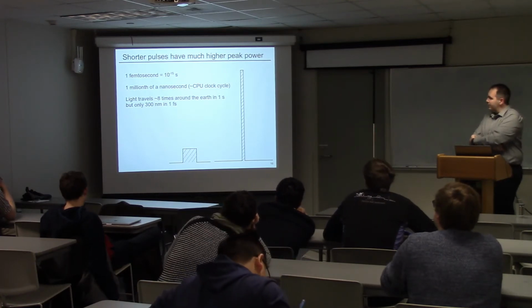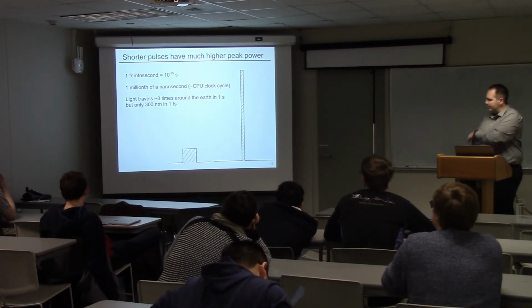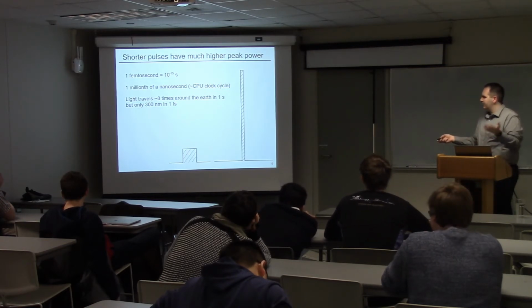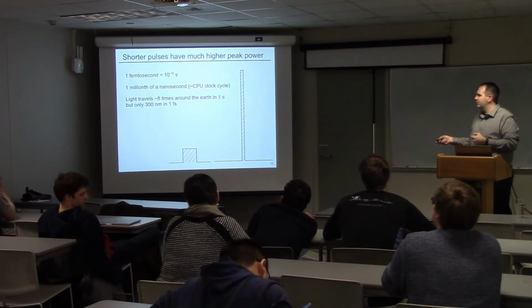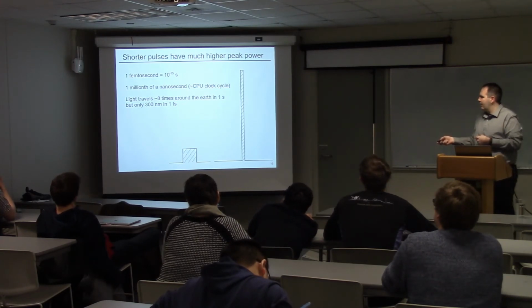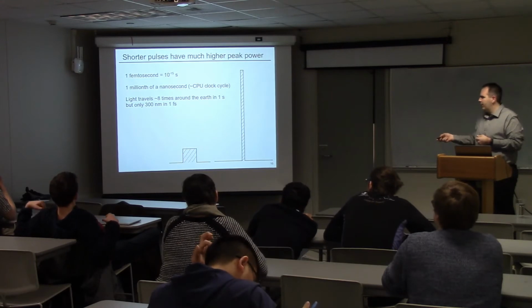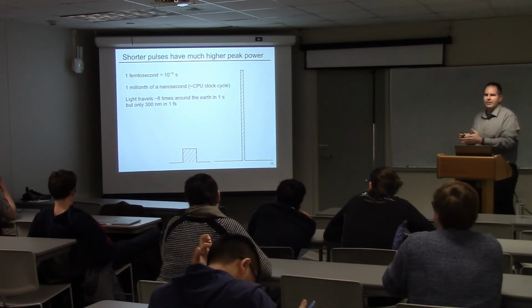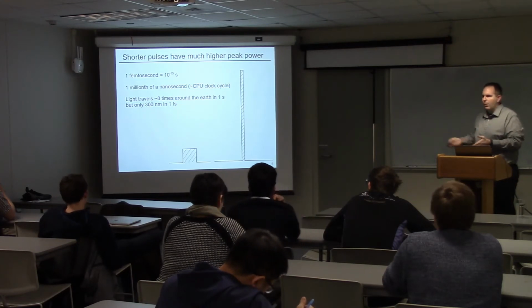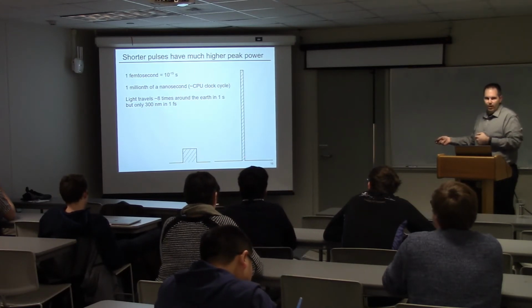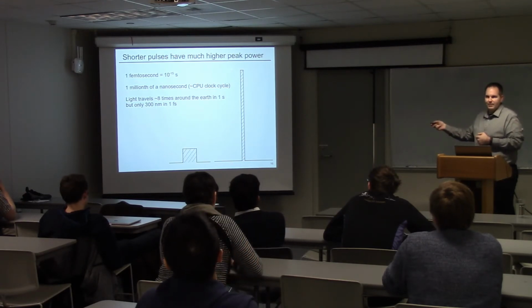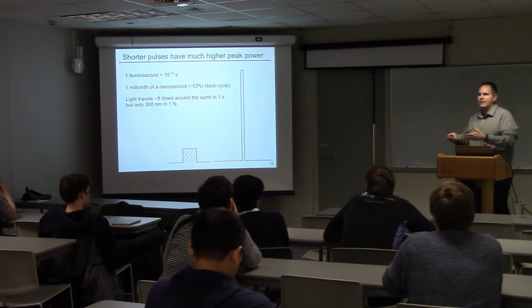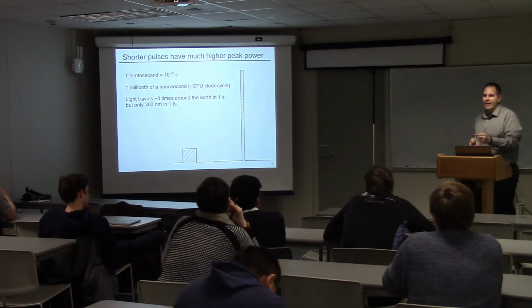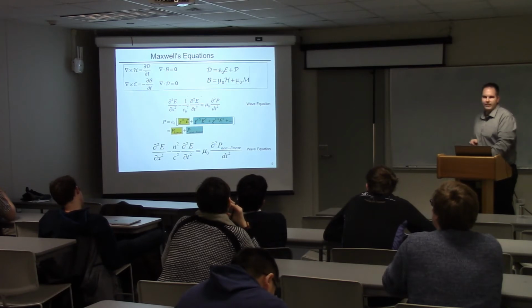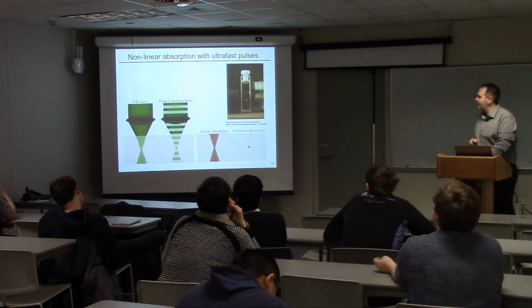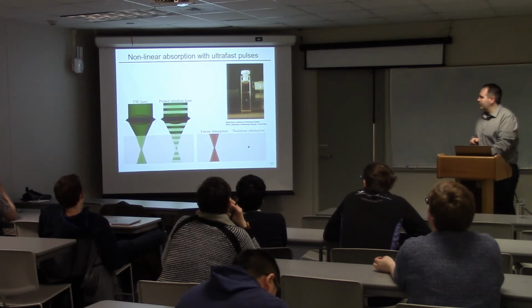So what we do with short pulse lasers, another way to imagine it: if you have a pulse, which would, for example, be a nanosecond pulse, and you have a certain amount of energy, then if this was time and this was power, the integral of that, the area under the curve, would be energy. Let's say you want to take that pulse and compress it, and you want it to keep the same amount of energy. Well, what would happen would be exactly this. You would get a shorter pulse with a much higher peak power. When you focus that with the laser, you get a peak intensity, and those intensities can be really high. That's what allows you to turn on these nonlinear physics terms. Okay? So, nonlinear absorption with ultrafast lasers.